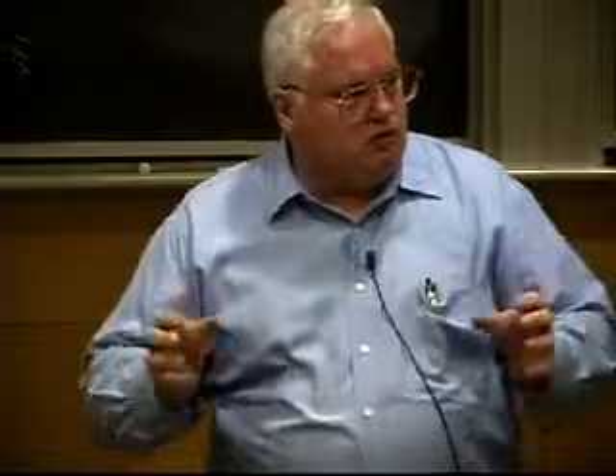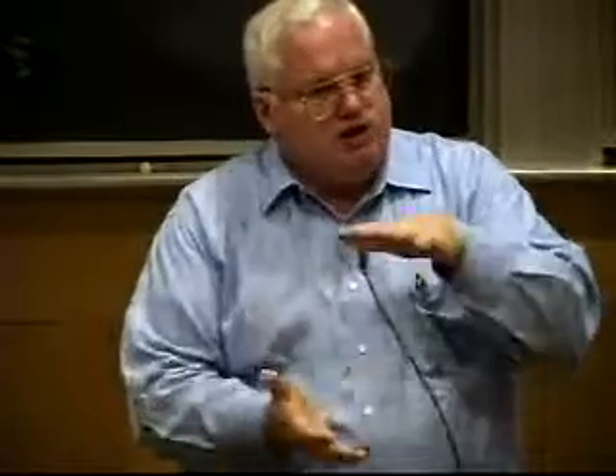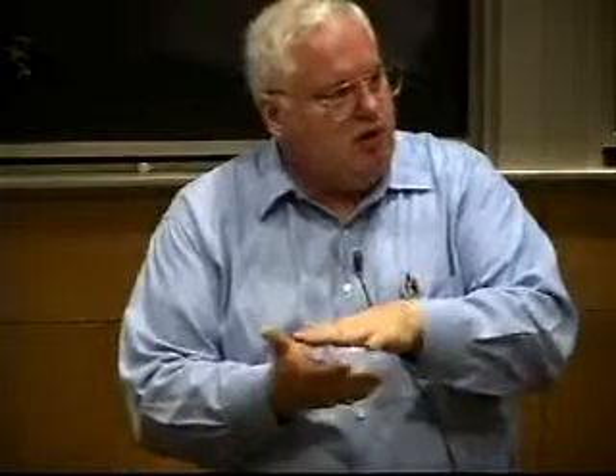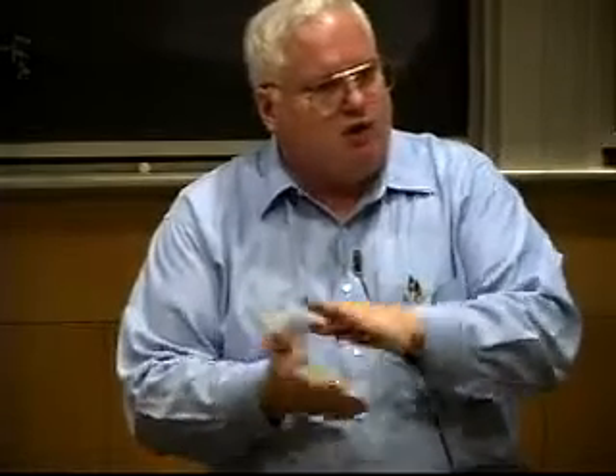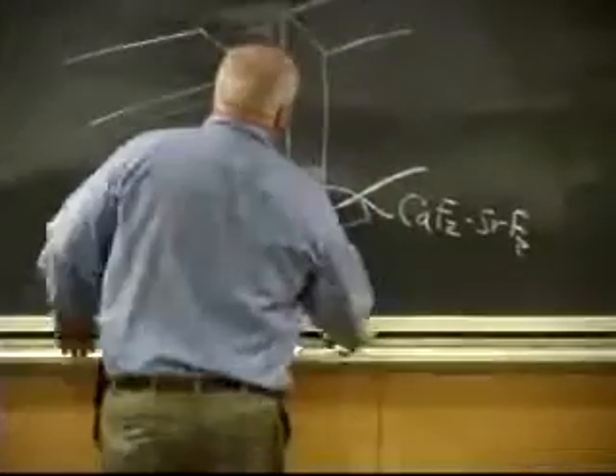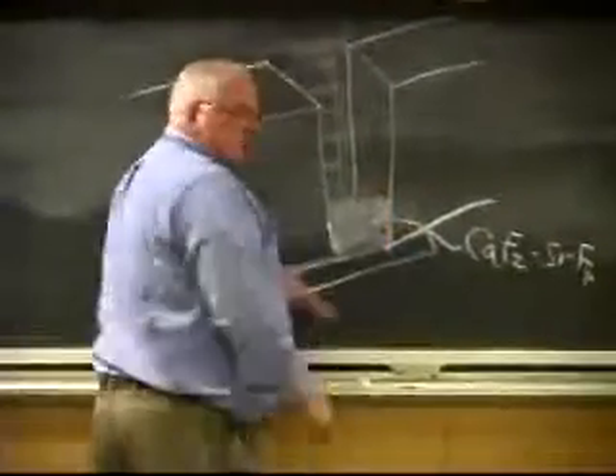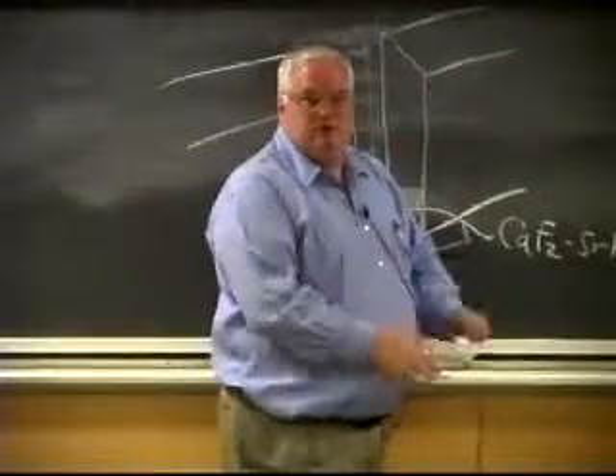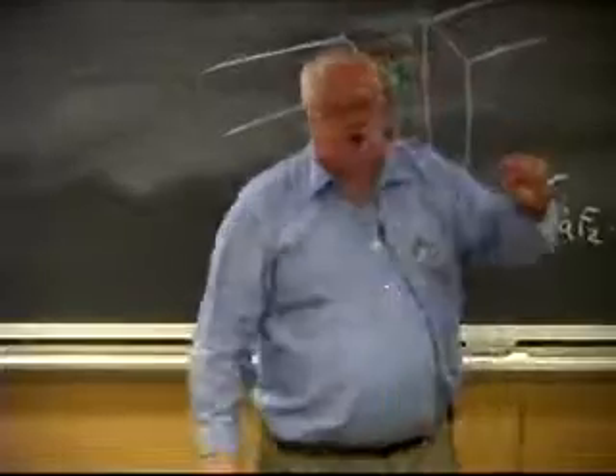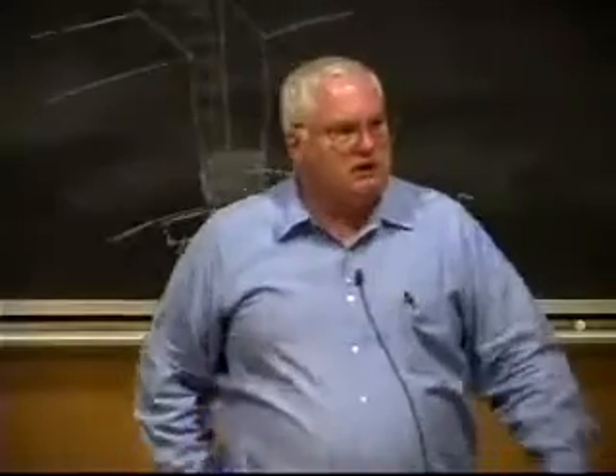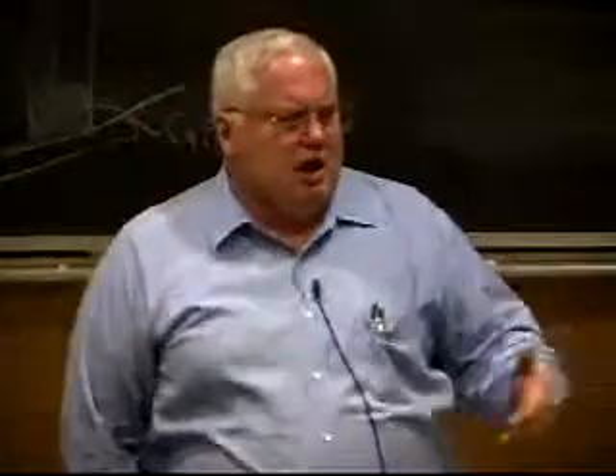Okay? Like you needed a tool steel with very small inclusions and uniformity. You're basically taking a big ingot and giving it a small casting volume, because the solidifying layer of metal here is basically just a little weld pool, if you will. It may be half an inch deep. It's not a great big 2-foot wide casting. It cools very quickly, so you can get a very homogeneous, relatively fine-grained structure.